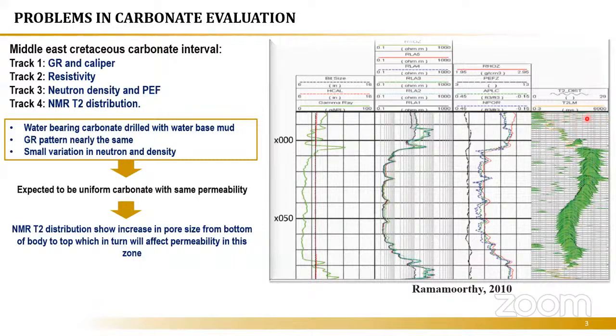As this time scale increases, a high value indicates a larger pore size, but this condition is only applicable if you have a water-bearing reservoir, because the NMR depends on three processes: surface relaxation, bulk relaxation, and diffusion relaxation. If you have a water-bearing reservoir, the bulk relaxation and diffusion relaxation will not have an effect on your T2 distribution. So the T2 distribution here will reflect your pore size, whether you have big pores or small pores.